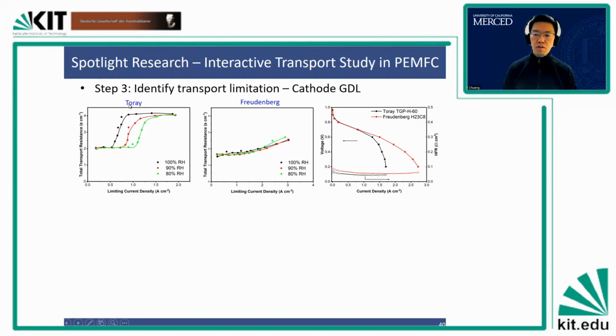Because for the Toray, you can see that at high current density, you have very high oxygen transport resistance, right? Low current density is good, but high is bad. That's why you see this very dramatic drop in performance. On the other hand, for Freudenberg, you can see that the increase of the transport resistance is not so high, so it continues to be able to run at a high current density. And we also identified that this happens on the cathode side, so we know that this is from the oxygen transport limitation.